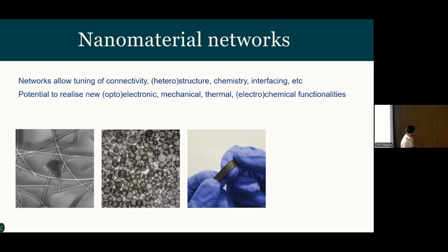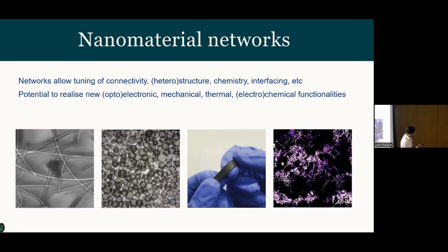And the main interest in that is we can then scale these things up to make macroscopic sensors, for example. This is actually conducting AFM images, so we can map current paths in these systems. So we're looking at very applied properties of these systems. Because we keep the processing very simple and scalable, we can tune the processing on demand, and we can tune the kind of systems that we can make for sensors, for energy applications. And we're working with various industrial partners. We're predominantly industrially funded working in this area.